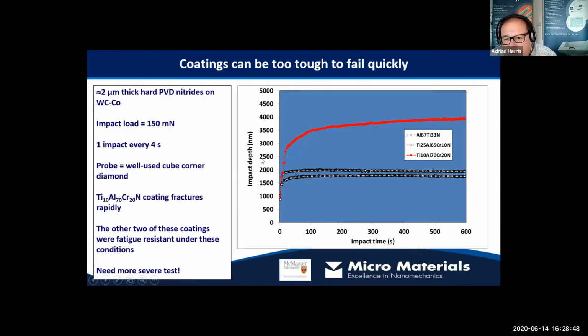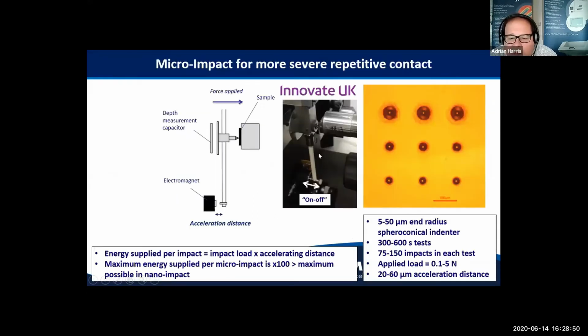So what we've done is we've adapted our high load instrument. So this is actually our micro indentation head. We've adapted that for impact, and now we can impact with much higher forces. We can accelerate the probe over bigger distances, and we can deliver much more energy in an impact test. So we can actually deliver now up to about 100 times what is possible in a nano impact test.